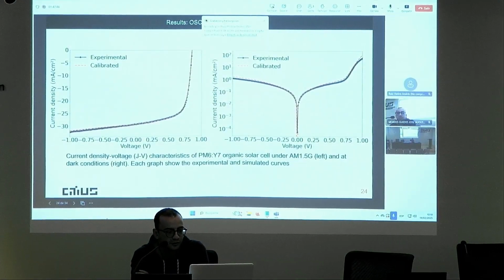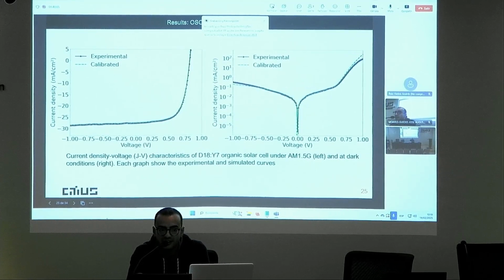This figure shows a comparison between the experimental and the calibrated curves of the PM6 organic solar cell under both illuminated and dark conditions. Note that the simulated curves perfectly match the experimental ones, validating the accuracy of our modeling. Similarly, in this case, from the D18 organic solar cell, we have the same behavior. Both calibrated and experimental curves perfectly match, validating the accuracy of our modeling.